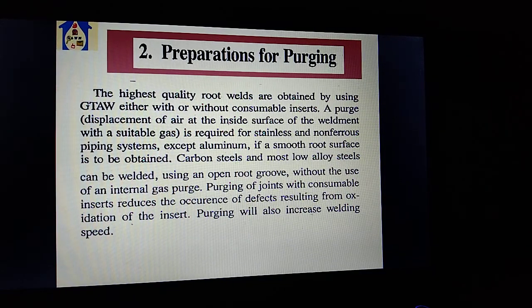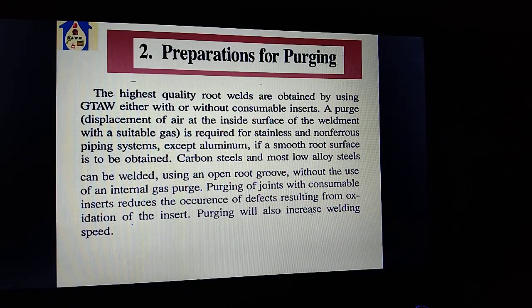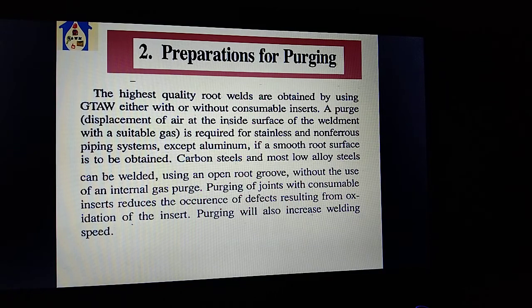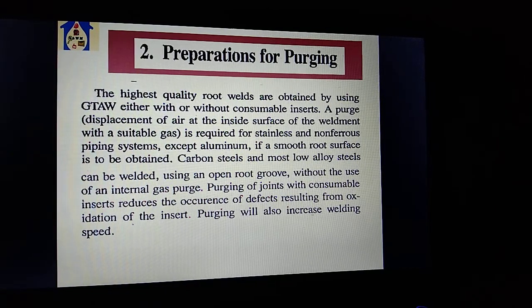If a smooth root surface is to be obtained, carbon steel and most low-alloy steel can be welded using an open root groove without the use of an internal gas purge. Purging of a joint with a consumable insert reduces the occurrence of defects resulting from oxidation of the insert. Purging will also increase welding speed.